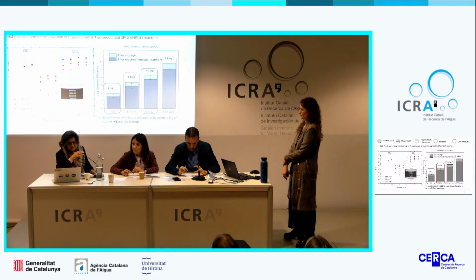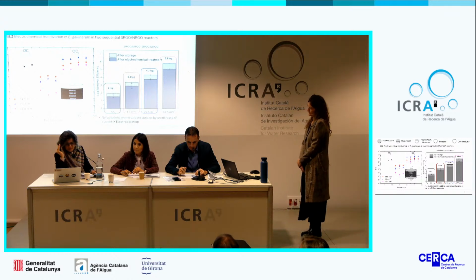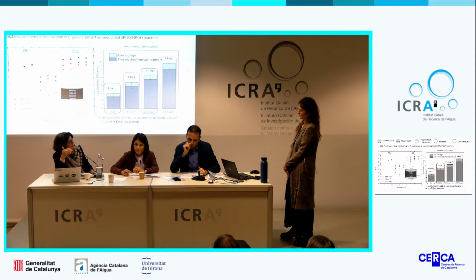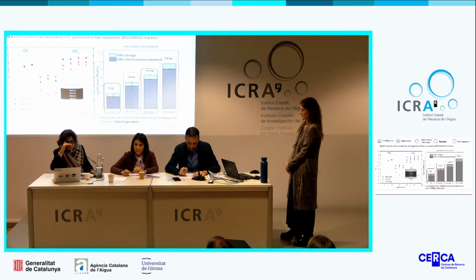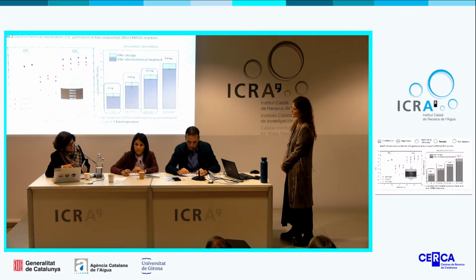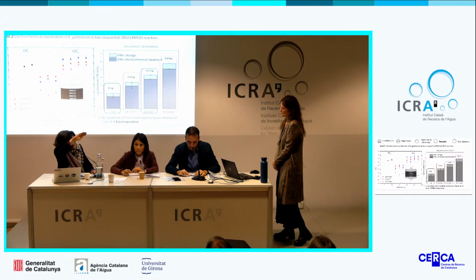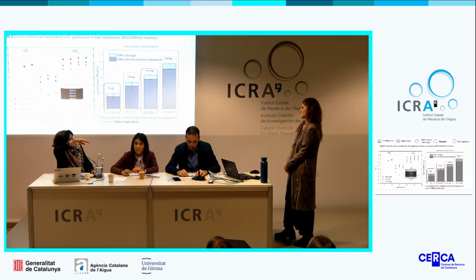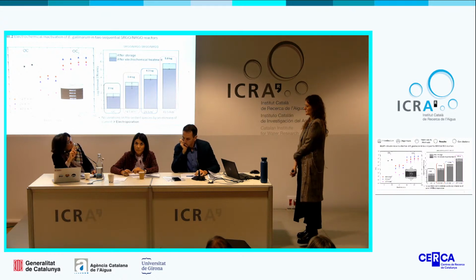Regarding hydrogen, you explain that a higher current leads to greater production of bubbles, hydrogen and oxygen. It's why the higher current causes a decrease in the removal of some antibiotics. It was on page 100. Okay, you increase your current, and the removal is not so good after a certain value. But it was not the same case for each antibiotic.